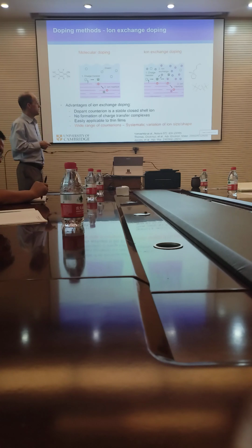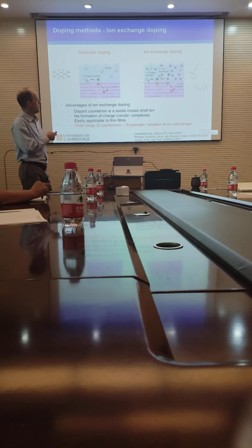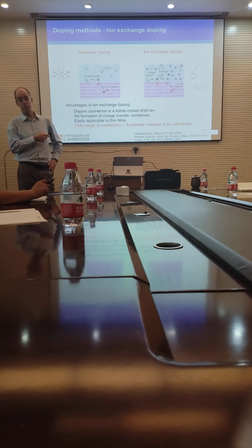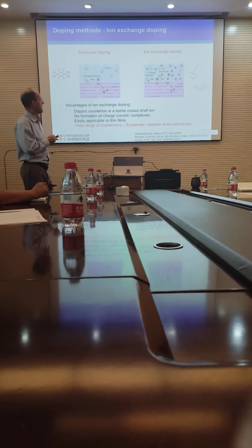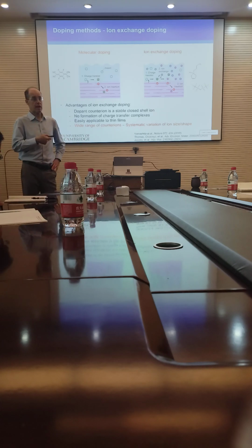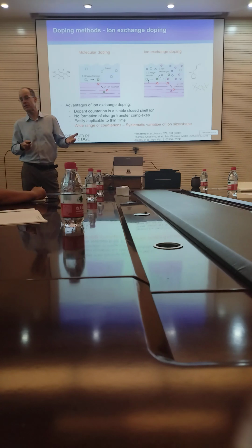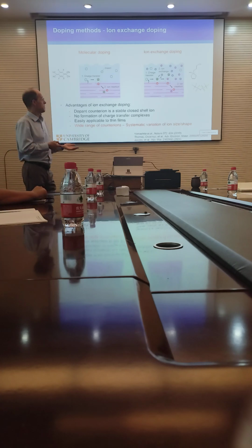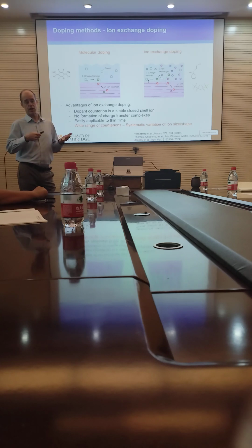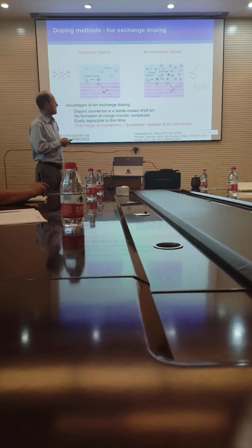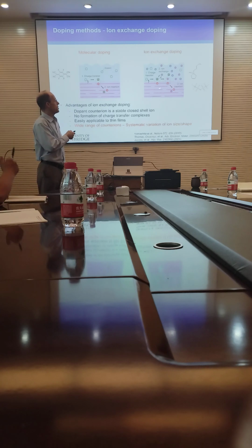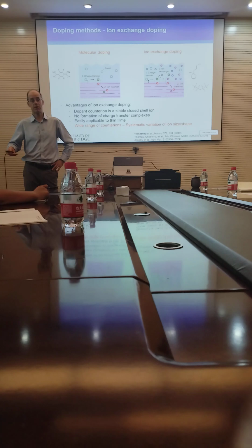In the ion exchange doping method, for example, here we have a film that we want to dope, and on top of the film we have an electrolyte that contains a molecular dopant as well as an ionic liquid. And then the molecular dopant, for example, ferric chloride, can be used to induce the initial electron transfer from the polymer onto the dopant molecule. But then on the surface, the molecular dopant anion gets exchanged with the ionic liquid negative ion. And then what gets incorporated into the organic film is the ionic liquid anion together with the hole that you've generated on the polymer chain.